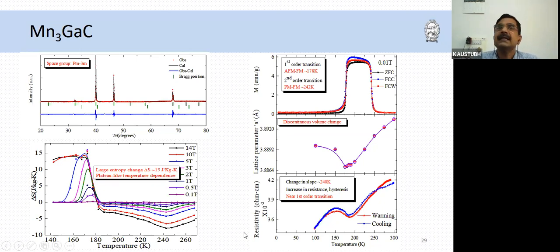We also measured the entropy, and the entropy of this material shows a plateau-like structure, which is what those people who want to make applications out of this in ferroic cooling desire, that this plateau-like behavior should be there. But yeah, it is at very low temperature and at very high fields. But nevertheless, this is a very good or a probable good material for application. So this was all fine.